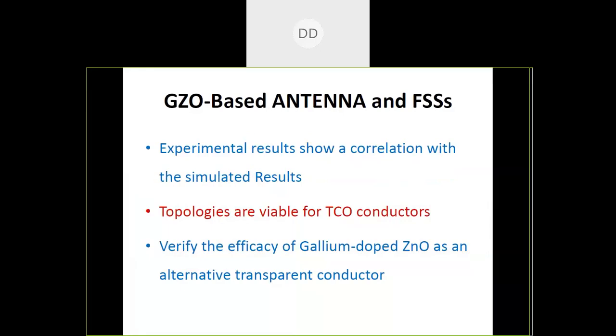So this study of the experimental results of the proposed filter and antenna has shown that there is a correlation between the simulated and the experimental results. So such topologies are viable for TCO conductors. So we can use this gallium doped zinc oxide as an alternative transparent conductor. So the whole purpose of this study was to study the efficacy of this gallium doped zinc oxide as an alternative to ITO.